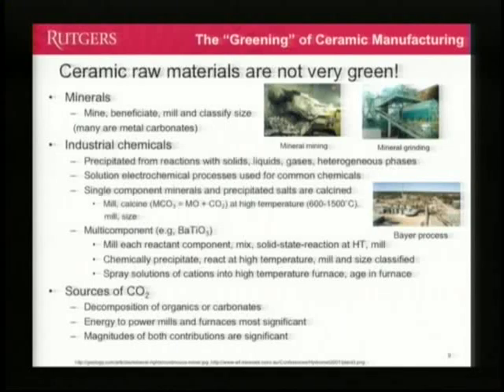So most frequently, they're in carbonate form and they release CO2. And that's a big deal. You're going to see that almost the same amount of CO2 that's released in the calcination stage equals approximately what it takes to fire the material. So you literally, when you work with a carbonate, double your CO2 that actually comes out.